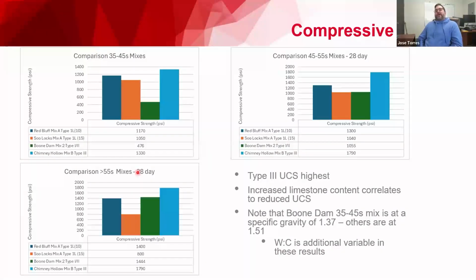In terms of compressive strength, not really a surprise here, but in the 35 to 45 second range, type 3 had the highest unconfined compressive strength when we broke them. The lowest was the type 1-2 here, which is a little bit weird, but generally the 1L cements acted similar in the 35 to 45 second range.